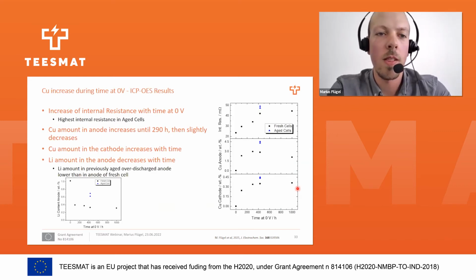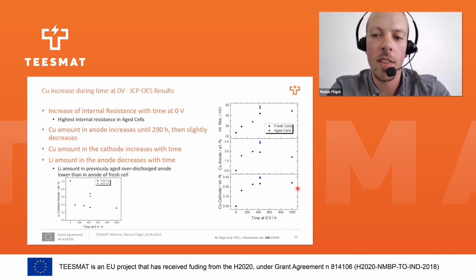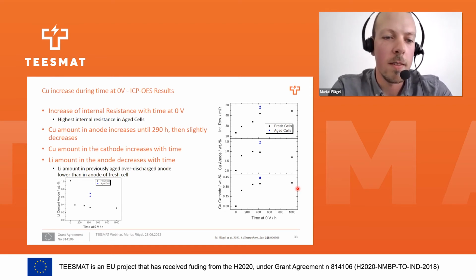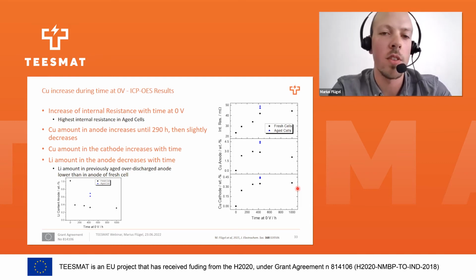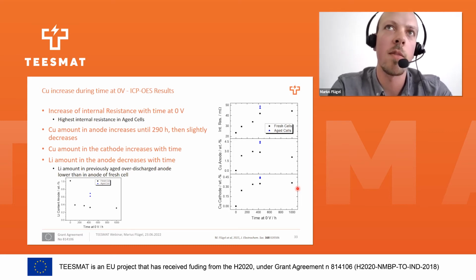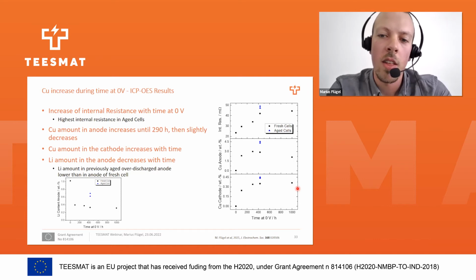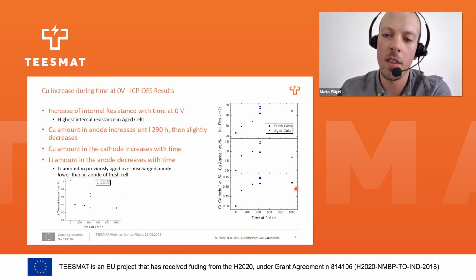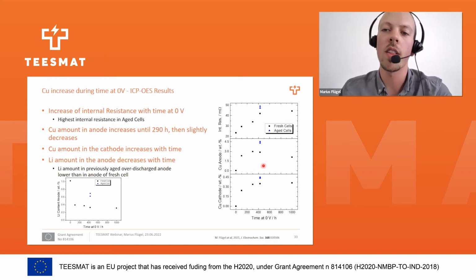We used ICP to investigate the lithium and the copper in the anode and the cathode. For the lithium amount in the anode, we saw a decrease of the lithium after over-discharge, which was probably due to the SEI decomposition due to the high anode potentials, and then the migration of the lithium to the cathode. And we also saw a sharp increase in the copper amount in the anode, which can be seen here, and also an increase of the amount of copper in the cathode, which then probably migrated from the anode to the cathode. The highest amount of copper was found for the previously aged cells.